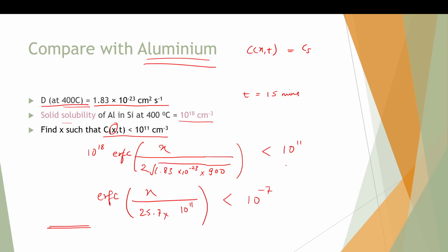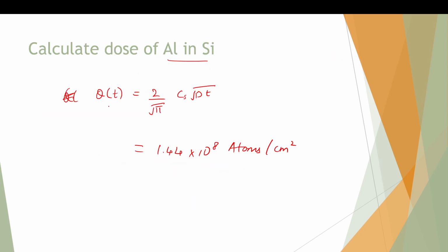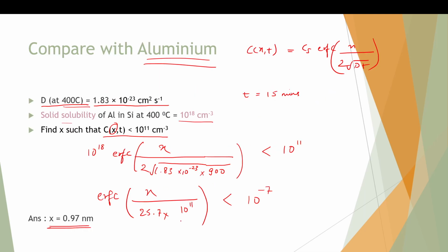So just by substituting in the equation, Cs erfc(x / 2√(Dt)), we get that x should be equal to 0.97 nanometers, and then we can calculate the dose. I have not done it here, but we can just substitute and check; it comes out to be of the order of 10^8 atoms per centimeter square. So for aluminium, the dose in silicon is 10^8, and the x for which we get 10^11 as our concentration is 0.97 nanometers.